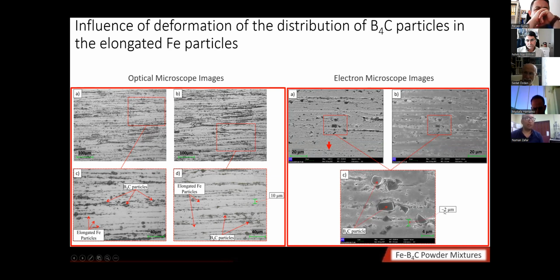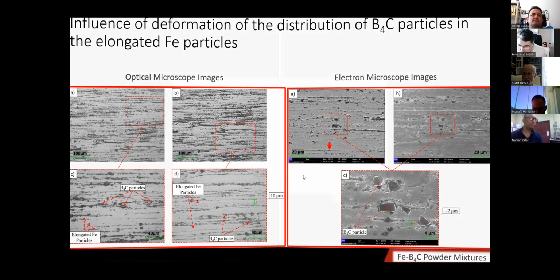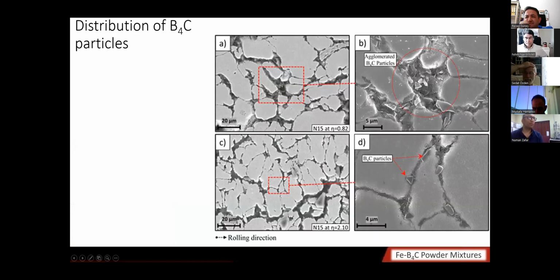But I can call this a microscale work because iron particles of 2 micron thickness can also be witnessed. These are B4C particles, all of them, and these elongated particles are iron particles. This state of the particles is something which we desire. Here is a lower deformation level, agglomerated B4C particles, a higher deformation level, no agglomerated B4C particles here.